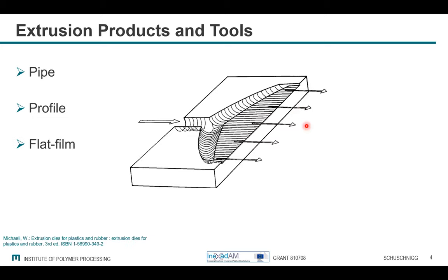For flat film dies, we can use, for example, a coat hanger die, where the goal is to get a very even distribution out of the coat hanger die here at the exit, so that over the whole width of this coat hanger die, we have the same velocities and the same thickness. Because what you don't want is to have thickness variations in there. There are different possibilities to calculate them analytically.